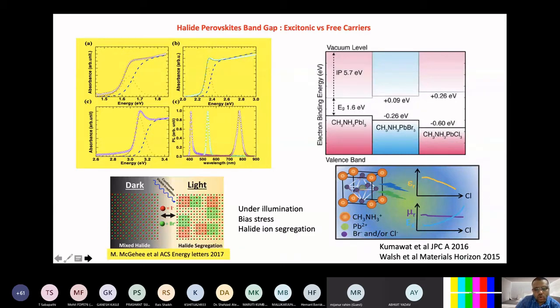Furthermore, we saw that we can mix them, we can have all color tuning. So this is what you have done. Red represents the MAPbI3 and green represents the MAPbBr3. But when you shine light on this mixed halide perovskite semiconductor and the light intensity is significantly high, then you find slowly this green starts coming together and red starts coming together. You start seeing light-induced phase segregation. Light-induced halide ion segregation starts taking place, and you find that they are no more emitting a single color, and they start emitting two colors of light. One corresponds to MAPbBr3 and one corresponds to MAPbI3.